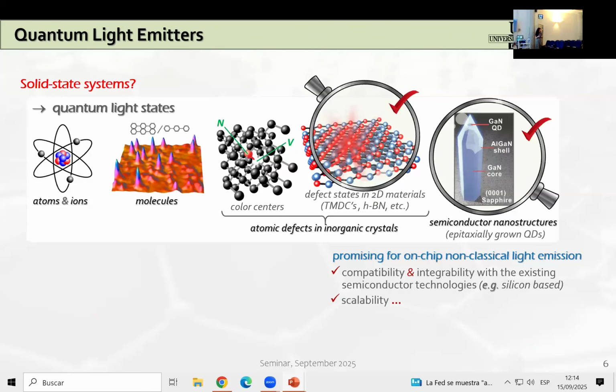So now the production of single photons is actually a quite competitive research field. It has been for a decade now, and there were many solid-state systems that have been studied for this purpose, like, for example, atoms or organic molecules, or atomic defects in inorganic crystals, which include color centers, the most known being the nitrogen vacancy in diamond. And as of recently, atomic defects in two-dimensional layered materials such as TMDCs, hexagonal boron nitride, or other materials. One can also use semiconductor nanostructures such as epitaxially grown quantum dots. Now, here I will basically talk about these two systems because they are quite promising for on-chip production of quantum light. And this is mainly because of their scalability and their interoperability with the existing semiconductor technologies, especially silicon-based technology, which is currently mostly used.